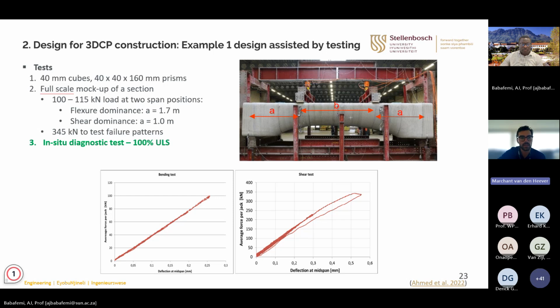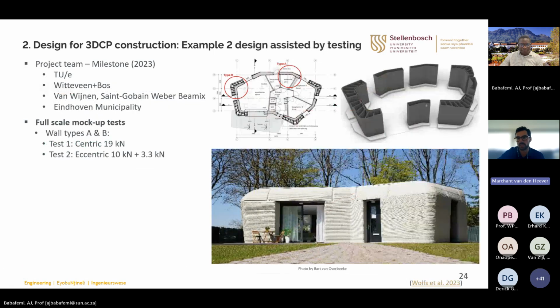And as we can see from the in-situ diagnostic tests, they were able to exhibit through the testing phase that 100% of the design ultimate limit state was able to be reached. So the 100 kilonewton in bending was achieved, and then 345 kilonewton shear capacity was shown. And from that, they were able to verify that the design was appropriate, and the project went forward, and it was really a great project.